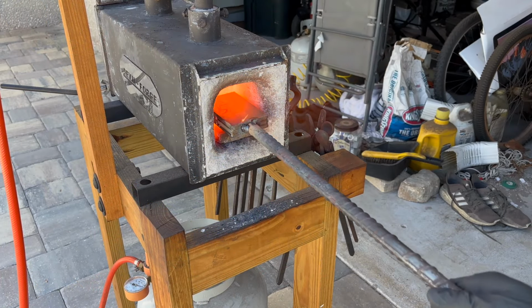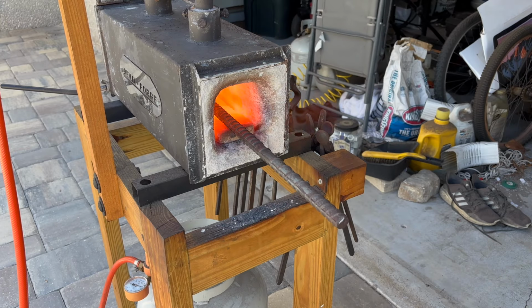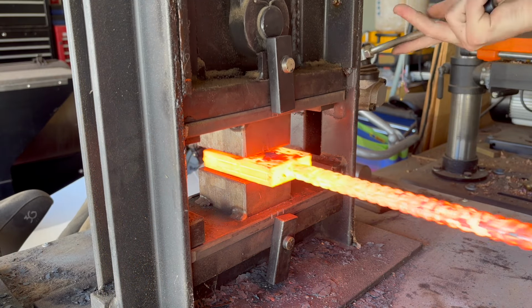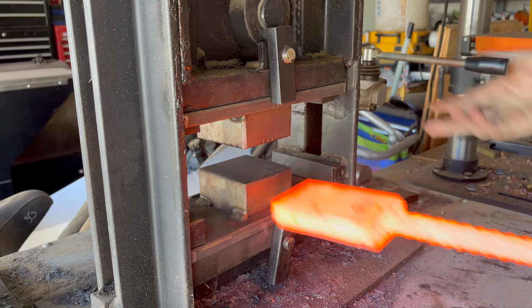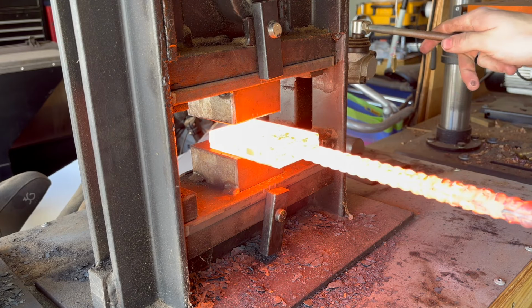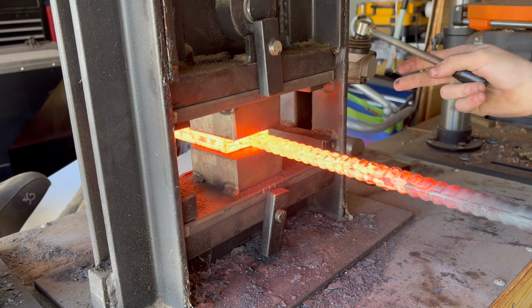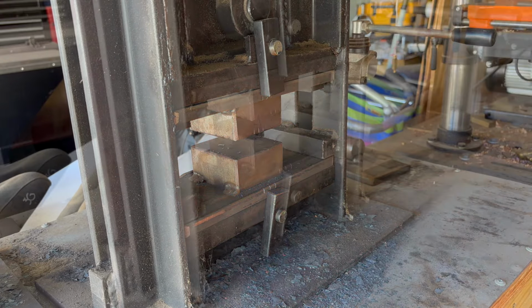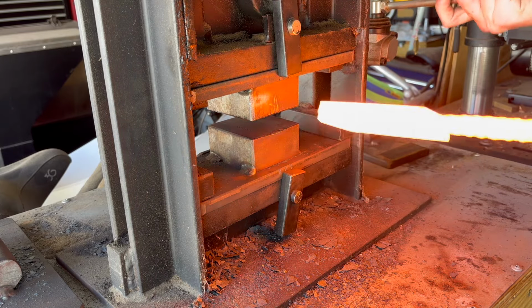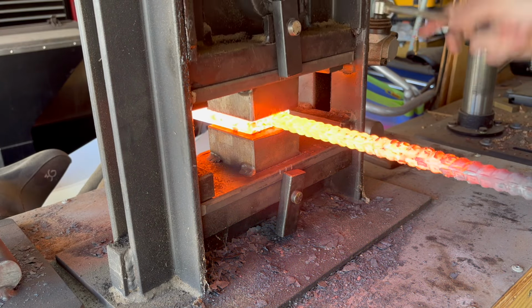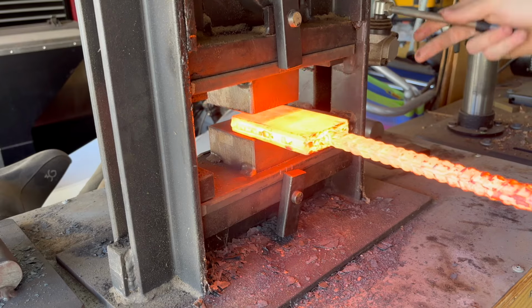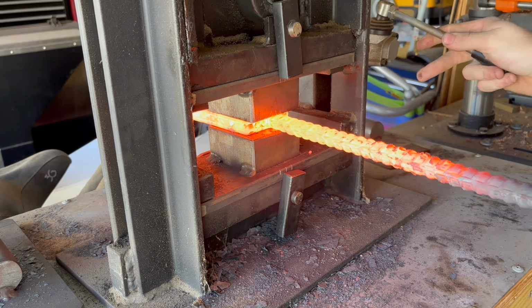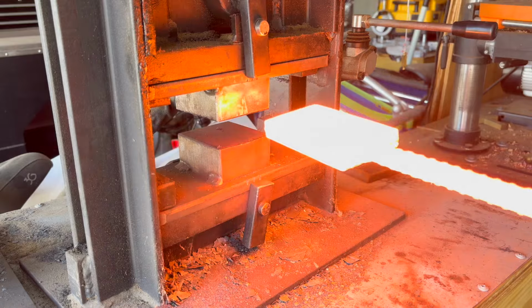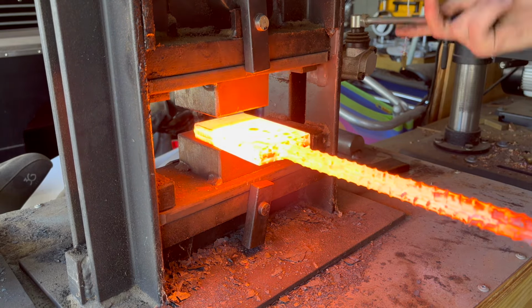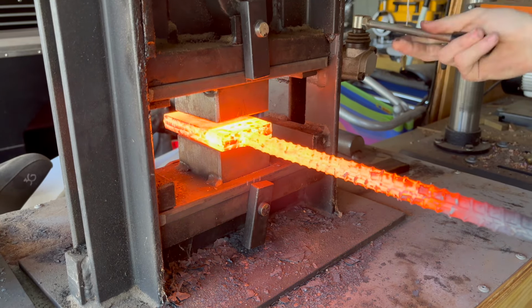Now it's going in the forge, and once it's hot I start setting the welds, and you'll see I do this 4 times, and I'm actually letting it soak in the forge for a few minutes each time to get the grain boundaries to grow past each other. And these are just really short, light passes just to get the welds set. And once I'm sure the welds are set, then I can start drawing it out using the drawing dies.